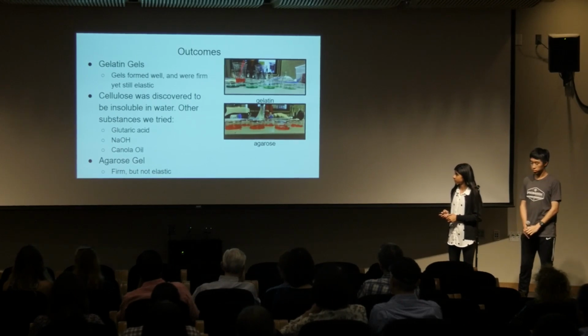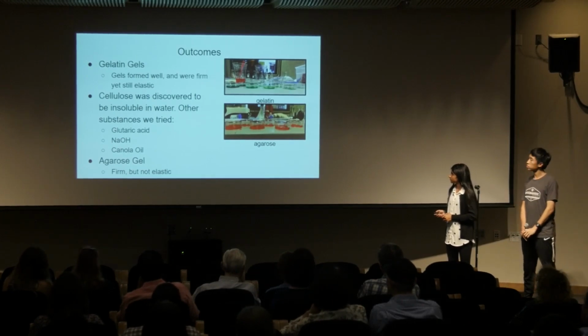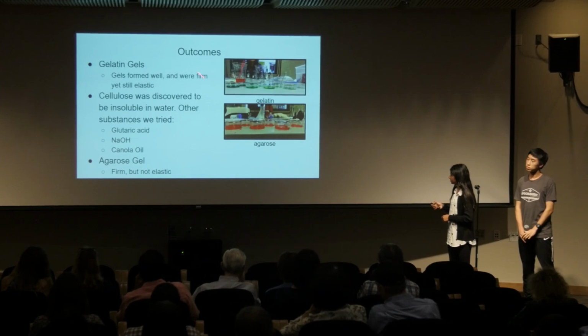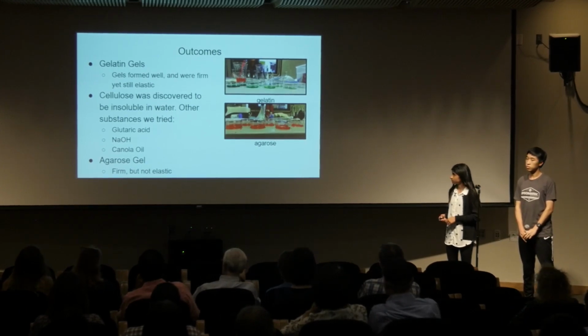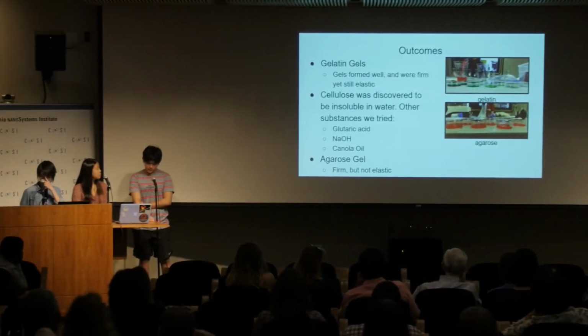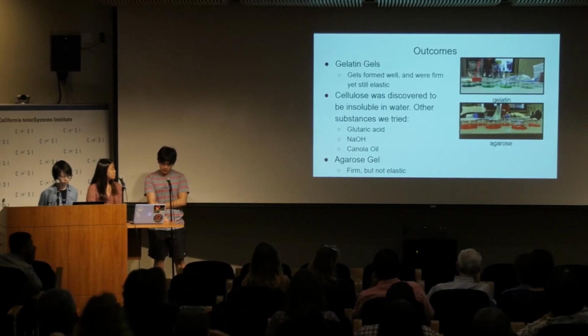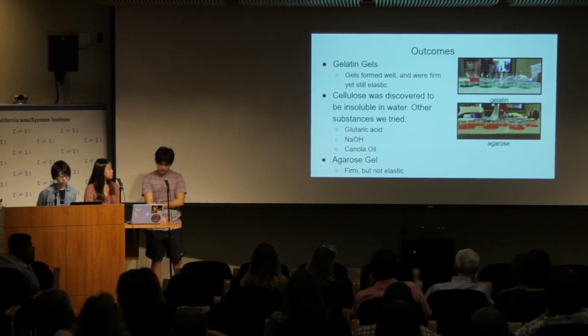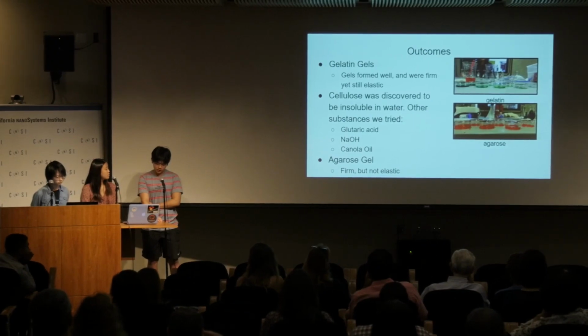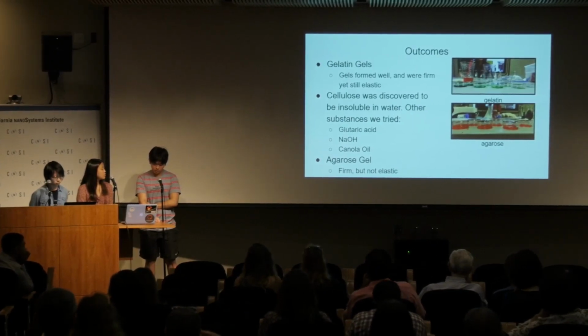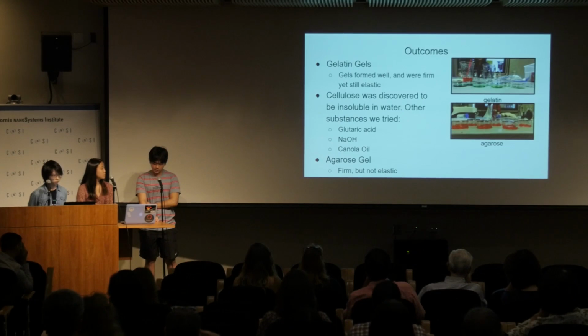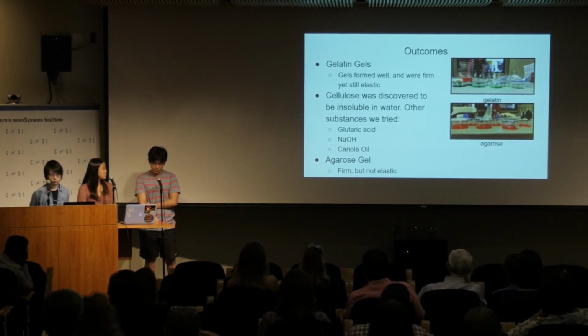During the experiment, we started with gelatin gels, and we were successful in creating a gel that was firm yet elastic. However, we weren't able to synthesize a cellulose gel. When we attempted to, we found that it was insoluble in water, so we tried to add a cross-linker, NaOH, and we also tried glutaric acid, and that didn't work. So we tried dissolving the cellulose in another solvent that was nonpolar, but none of these alternatives worked. Agarose gel did form, however, we determined it to be too rigid at all tested concentrations to be considered a viable skin substitute in regards to elasticity.